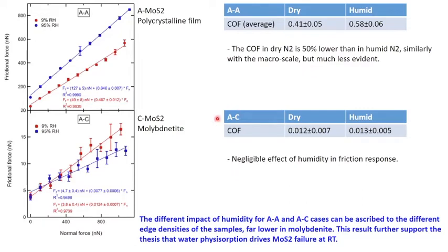When we move to the amorphous-crystal coupling, in this case, the coefficient of friction drops to 0.012 in the case of dry condition and 0.013 in the case of humid condition.